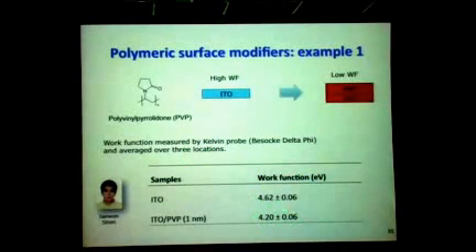When he did Kelvin probe measurements of ITO modified with a very thin layer of that PVP material, he could see a significant reduction in the work function, sufficient to turn ITO into a low work function electrode and an efficient electron collecting electrode, so you can turn the device upside down.